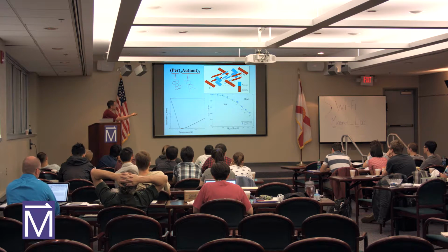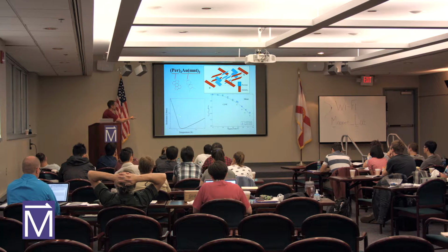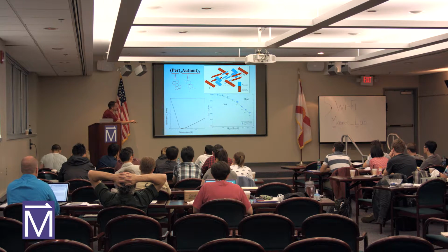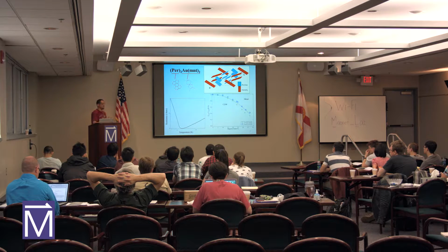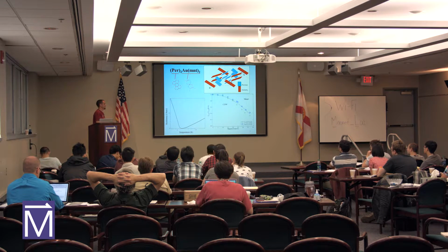So we make this phase diagram of the transition temperature, where this density wave transition happens, as a function of magnetic field. As we go out in magnetic field, the transition temperature moves to lower temperatures. At the maximum field in one of our magnets, 35 Tesla, we can lower the transition temperature by up to 60%. This isn't so much a measurement of the Fermi surface as a way we can manipulate the Fermi surface for these quasi one-dimensional materials with a really strong magnetic field.